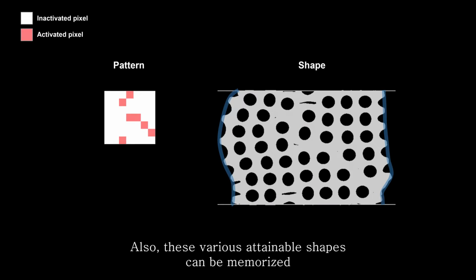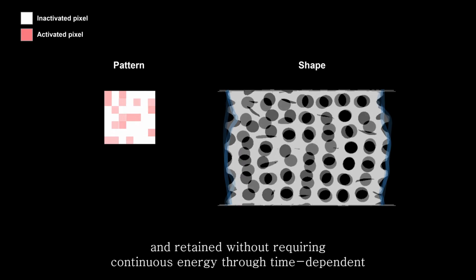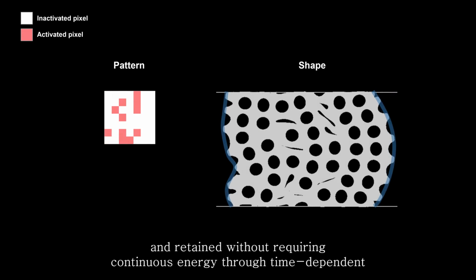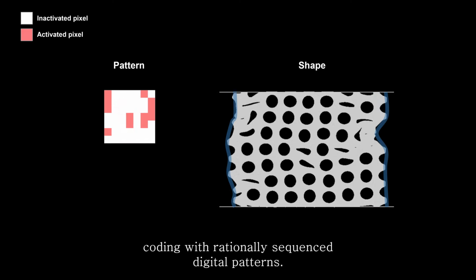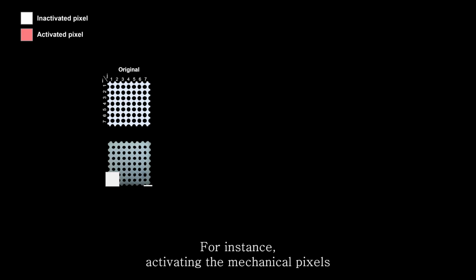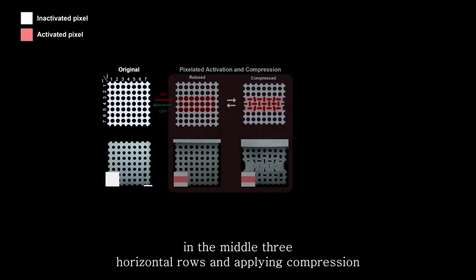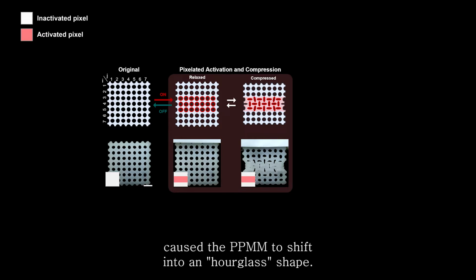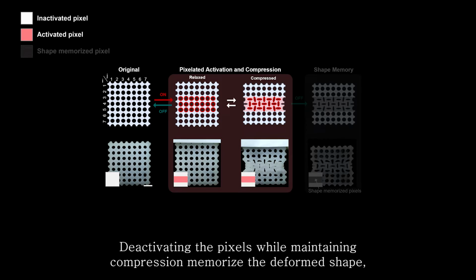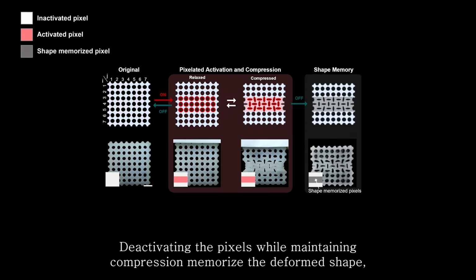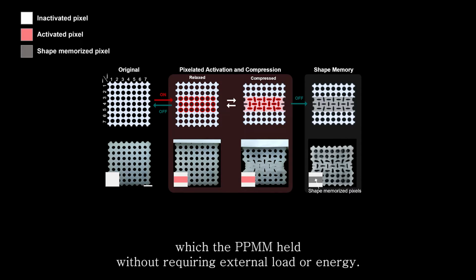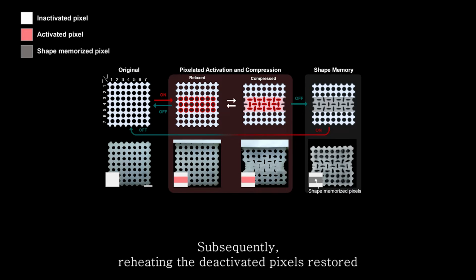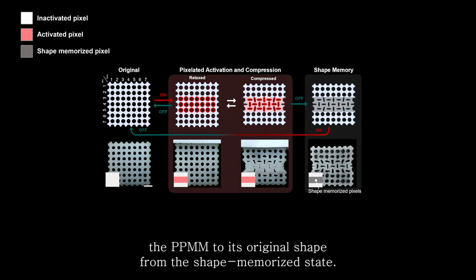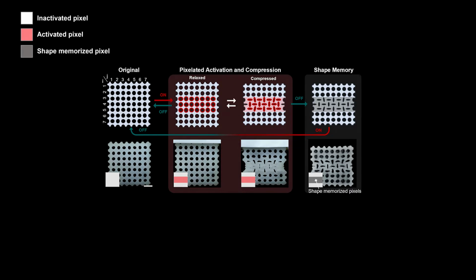Also, these various attainable shapes can be memorized and retained without requiring continuous energy through time-dependent coding with rationally sequenced digital patterns. For instance, activating the mechanical pixels in the middle 3 horizontal rows and applying compression caused the PPMM to shift into an hourglass shape. Deactivating the pixels while maintaining compression memorized the deformed shape, which the PPMM held without requiring external load or energy. Subsequently, reheating the deactivated pixels restored the PPMM to its original shape from the shape memorized state.